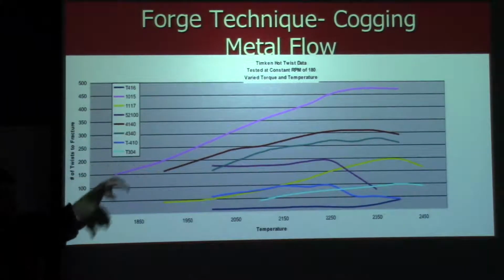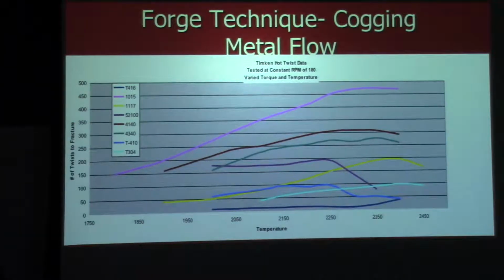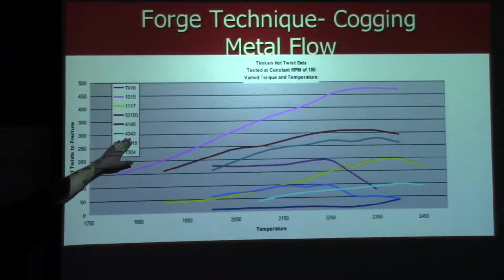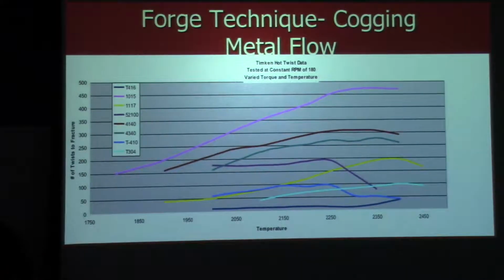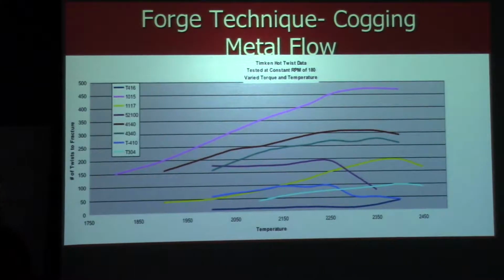So a 4140 is a steel that has about 1% chrome and about 0.25% molybdenum. And then 40 points of carbon. 4130, very similar, it's got the same chrome and similar molybdenum, a little bit less carbon. Your 4340 has chrome and molybdenum, just like the 41 grades, but then it has an additional alloying element, nickel, and the nickel in this case is in the range of about 1.6 to almost 2%. That nickel makes this grade much higher in hardenability than this grade. And we'll talk about what that means more in another lecture.